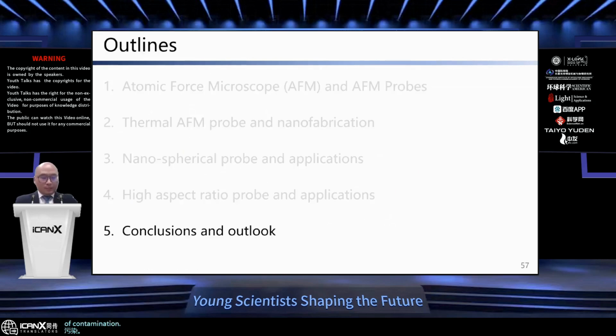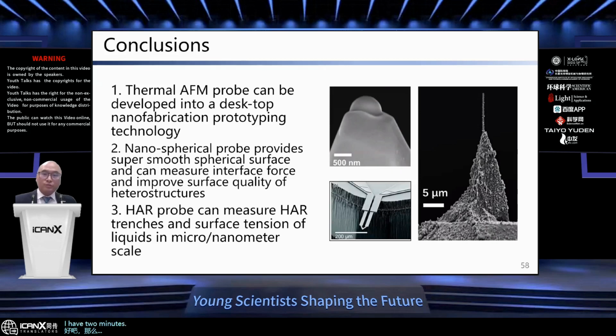Okay, so I have 2 minutes. I want to draw the conclusion. I hope I convinced you of these 3 unique AFM probes. A thermal probe can be turned into a desktop nanofabrication prototyping machine. A nanospherical probe gives you a smooth surface and can measure interface force very accurately. And the high aspect ratio probes can measure high aspect ratio trenches and the surface tension of liquids at micro-nanometer scale.